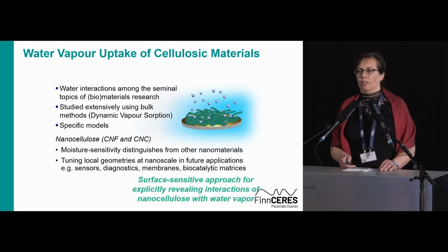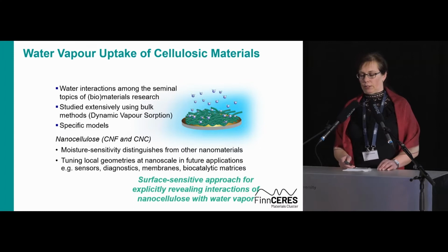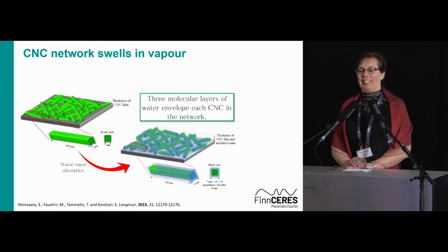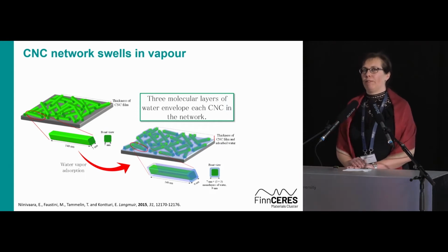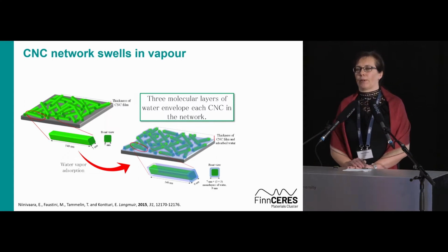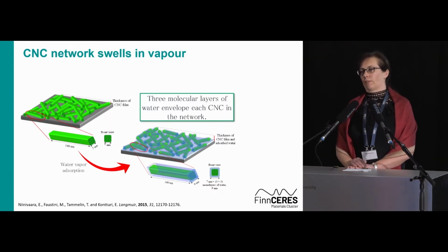And the next slide takes a little bit of time to appear because it contains so much information. It also dates back some years, before FinnCERES times, when we started to introduce this surface-sensitive approach, combining an acoustic method, QCMD, quartz crystal microbalance with dissipation, with an optical method, spectroscopic ellipsometry, to really look at the vapor uptake behavior of these cellulosic systems. And the simplest system was ultra-thin films of cellulose nanocrystals.